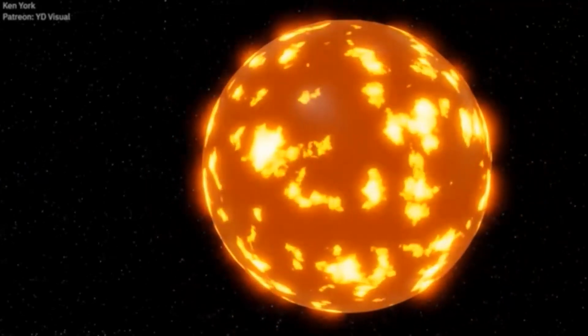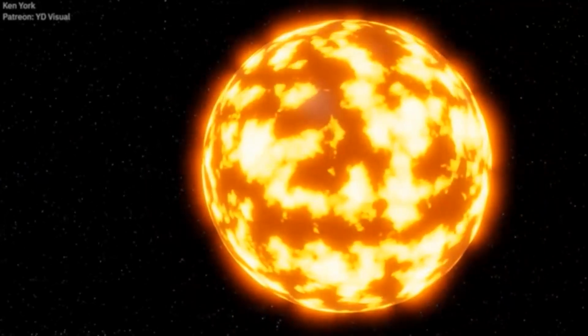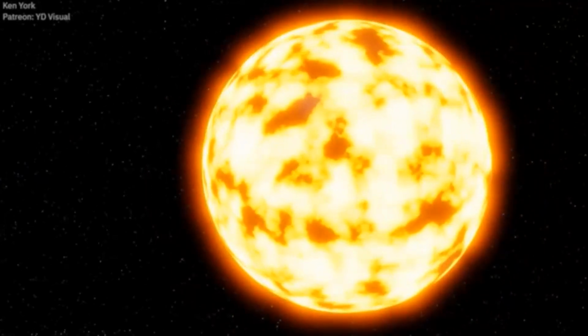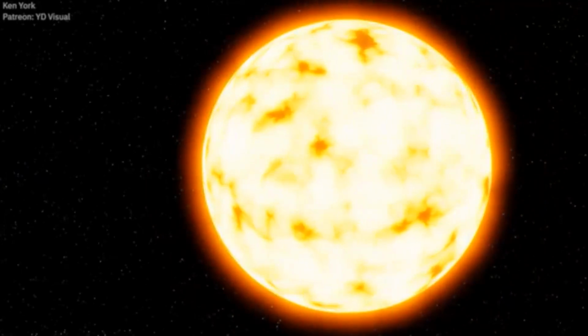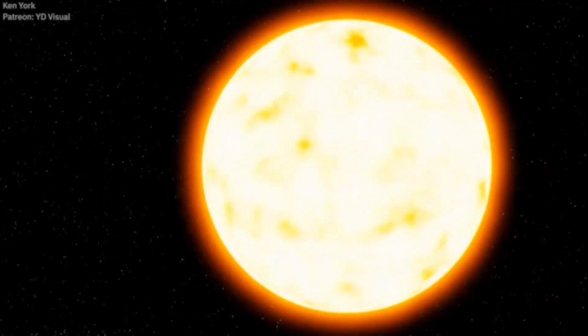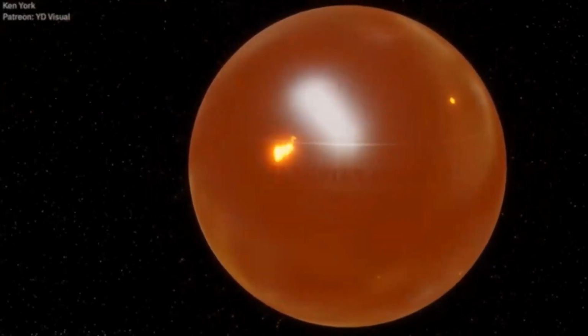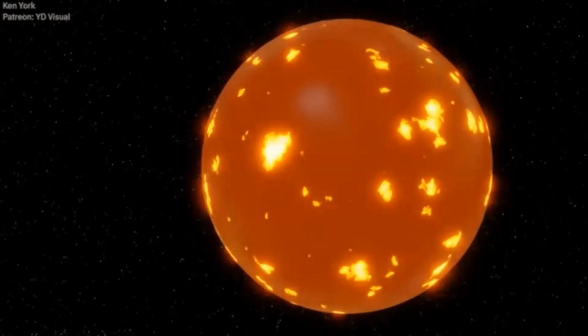And it's often alloyed with nickel, iron, copper, or even thorium to produce high-temperature sturdy materials with other necessary properties like electric conductivity. However, the new champion for highest melting point of a metal is an alloy of hafnium with tantalum and carbon at 7460 Fahrenheit or 4126 Celsius, vastly higher than tungsten. We also have had good results with hafnium alloyed with nickel and carbon. I should probably note that carbon actually has a slightly higher melting point than tungsten does as an element but not as a metal, and still falls short of this hafnium tantalum carbon alloy.